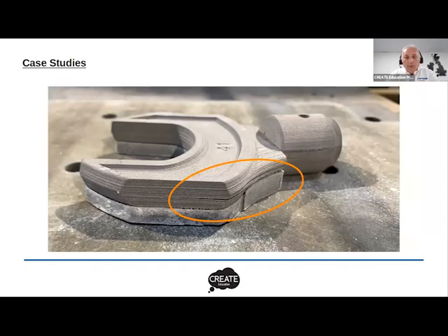It's not all perfect though. One of those parts had quite a significant crack in it, which is inside of that highlighted area. It's maybe not that easy to see amongst the layer lines on this picture, but I could get a piece of paper down that crack to about a depth of 4 millimeters.